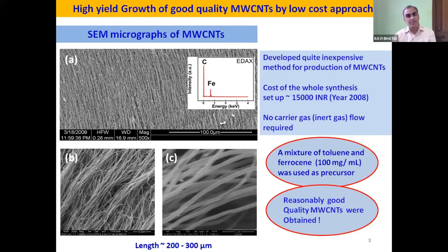Until you have the satisfaction in the production of your sample, don't go for the further experimentation, because it will not give you the justified results from the sample. For example, I will show in later stages that people have worked on the low temperature charge transport properties of multi-wall carbon nanotubes, and they have not presented a true picture of what they can give rise to. The electronic properties of carbon nanotubes have been considered to be very excellent. It should present metallic behavior, but people have observed variable range hopping conduction, which shows the exponential decay of conductivity with respect to the temperature.